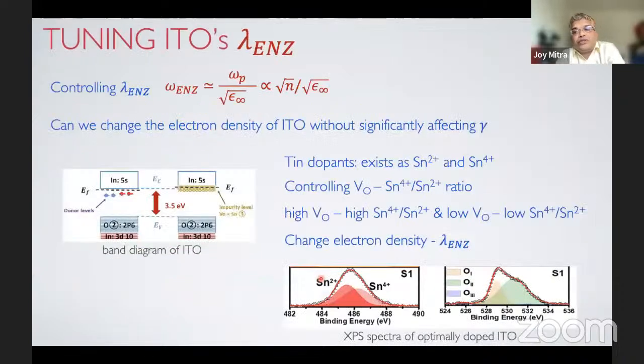Okay. Now, the first part was obviously to try to tune the lambda ENZ and see how robustly we can do that. If you look back in literature for many of these systems, we realize that the dopants are essentially the ionized tin states. This is the band diagram of ITO, and as you go on doping with tin, it creates these dopant states that donate electrons to the conduction band, with the Fermi level now lying firmly within the conduction band, and that's what makes it a conductor, or a transparent conducting oxide.